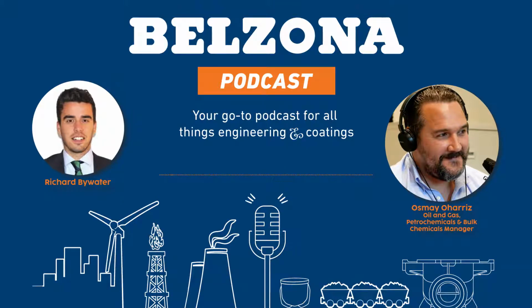So what we do is conduct what, for lack of a better word, I'd call fundamental chemical testing. Let's say we take a specific chemical, chemical X, at a maximum concentration of, let's say, concentration 1, and at a temperature as low as 20 degrees C. And we do the same at 90 degrees C. Then we assess the behavior of this chemical X at other temperatures and concentrations based on what we saw in those fundamental tests. This gives us an idea of what we could expect if we tested at a concentration of, let's say, 20% sulfuric acid, just to give you an example.